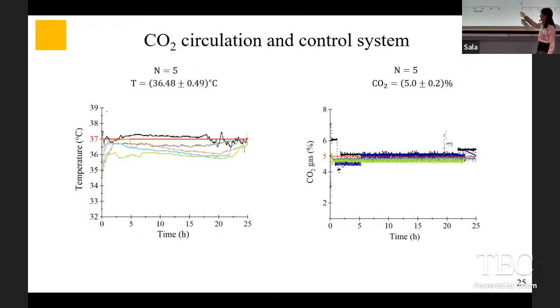circulation. We did 5 tests during 24 hours. And as you can see, temperature remains very close to the value that we wanted to achieve, that was 37 degrees. And it also happens with the carbon dioxide, which we also tested 5 times, and through the 5 tests, the system was always achieving 5% carbon dioxide. These both conditions are required for cell growth.